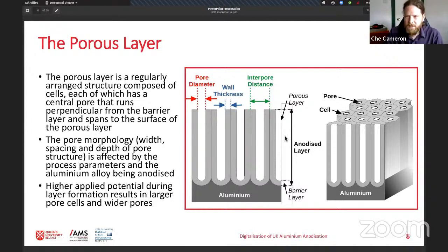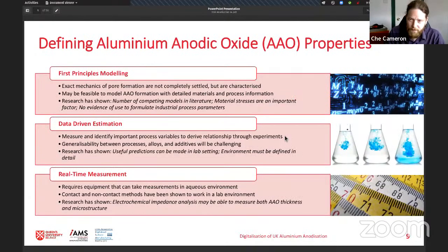And these structures are affected by basically all of the process parameters: temperature, voltage, and also the alloy and any additives. So it's quite a complex interaction that creates this pore. As a very rough rule of thumb, higher voltage means bigger pores. There's a lot that goes into it.